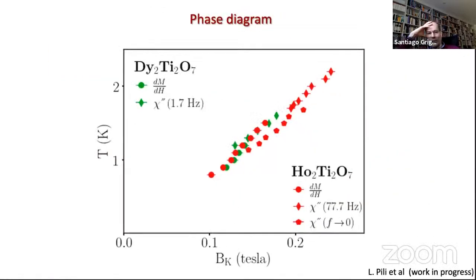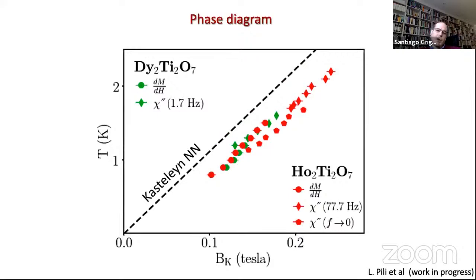So you can now construct a phase diagram using both dysprosium and holmium titanate. As I said, if you're looking for something that is independent of the exchange constant, you expect to find a universal line, and that's indeed what you find. If you now compare this line, where green is dysprosium and red is holmium, and these are different measurements we've done with different techniques, you see that, within experimental errors, you get some sort of line. You compare that with the Kasteleyn line you calculate in the nearest neighbor model, and you see that it's similar, but it's not exactly the same.